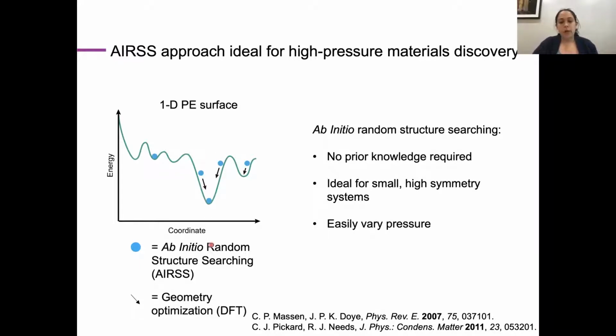We then perform a density functional theory based geometry optimization, which sends those balls to the bottom of the nearest well. And because of that rough correlation between well depth and the stability of that structure and well volume, if we can sufficiently sample phase space, we have a good chance of discovering the stable structures that we're going to find in experiment. And this is an ideal approach for doing high pressure research because strictly no prior knowledge is required, which is useful when we might not have any intuition for the types of structures we might get.